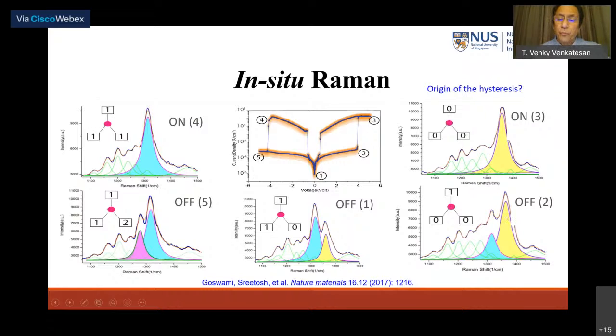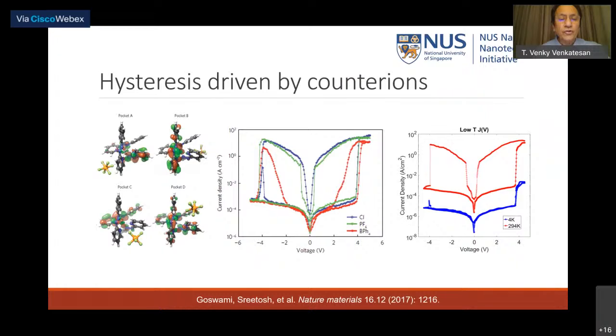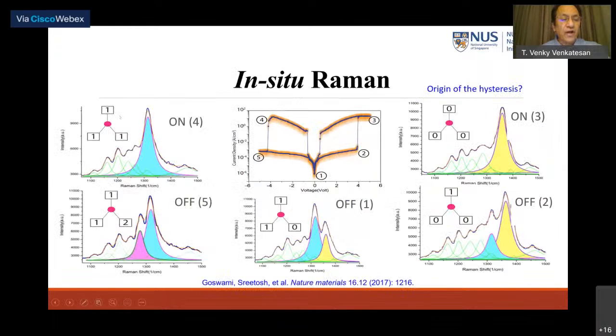And when I come to the switch point, position 3, all the modes are now at 0, and therefore the molecule's redox state is now 0 0 0. Similarly, when I come to position 4, you see that it's in 1 1 1, and finally switches down to 1 1 2, and then finally comes back to 1 1 0. Okay. One of the interesting things that you notice is that in the so-called off state, that is, where the conductivity is low, the redox states are dissimilar. That is, at least one ligand is in the wrong state. Whereas in the on state, you notice something interesting, that all the redox states are identical, like 0 0 0.